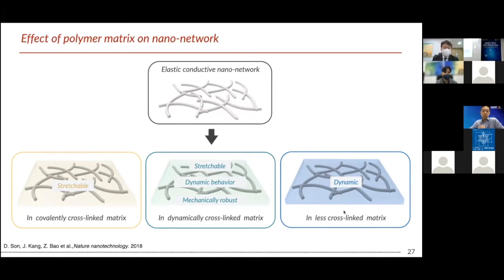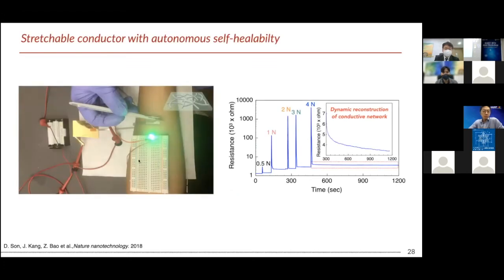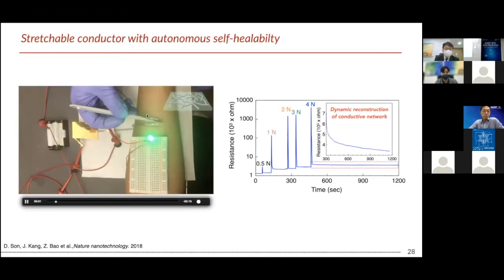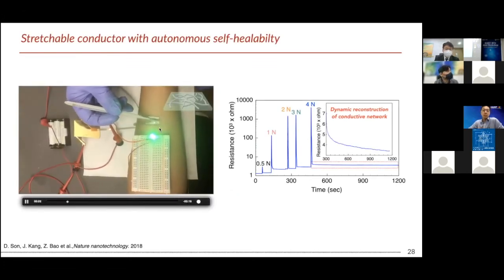And we found, with a very big surprise, that upon embedding this nano network into the self-healable polymer matrix, the nano network also starts to have very dynamic properties, and they can reconstruct their nano network under mechanical stress. So here's a video. We prepared the electrode and we start to scratch it with a razor blade.